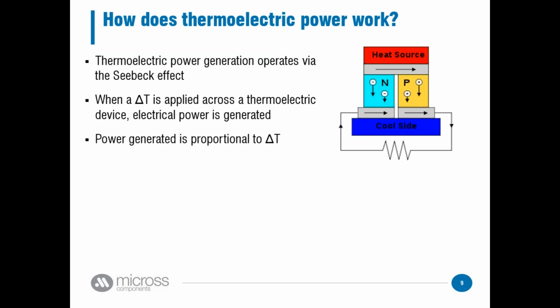So we talked a little bit about the materials. Now let's go a little bit into the nitty-gritty of how thermoelectric materials work. What's the mechanical behavior that we're seeing here? Essentially what you have is a thermoelectric device, a nice picture from Wikipedia, where we have an N-type material and a P-type material. You have a heat source up here, and you have your bottom side sunk to a heat sink. So you have a hot side and a cold side, heat sunk, and a very low thermal conductivity material here, so you've generated at this point a delta T.